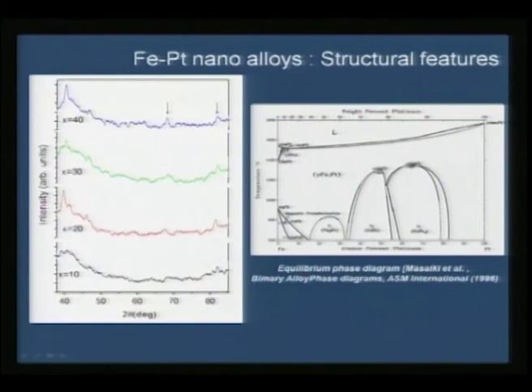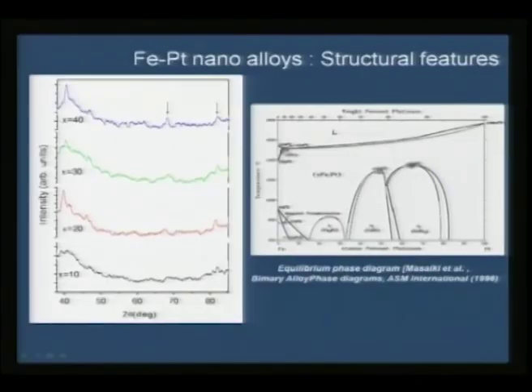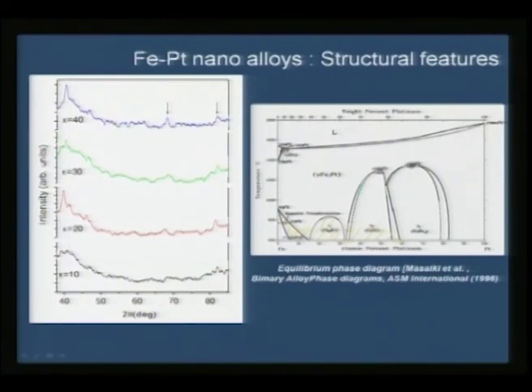One is there are several regions where the equilibrium phase diagram indicates there are magnetic phases as well as non-magnetic phases. For example, in this case you have alpha Fe phase, and this is the region where the alloy is magnetic, and this is the region where the alloy is magnetic. And there are regions where because of order disorder transformation you do not see magnetic phases. So if there are no magnetic phases in between in this region, then those regions should not show magnetoresistance.